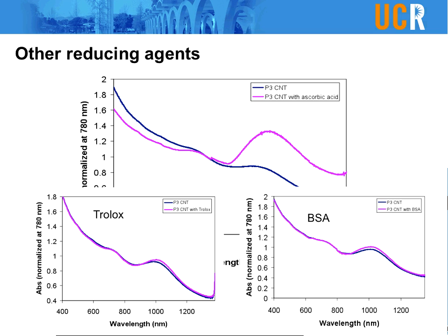We also analyzed the oxidation of other small reducing molecules, Trolox and also vitamin C, because we found these two could suppress the DCF oxidation in the previous experiment. So at first we assumed that the suppression effect is from the competition of oxygen in the solution, because both of these two are very strong reducing agents. So if they are stronger than DCFH, they will consume the oxygen first, and the DCFH would not contribute the electron to oxygen, so it will not be oxidized.